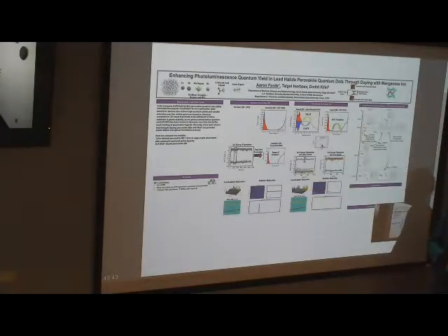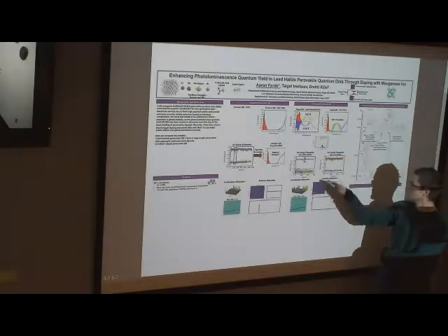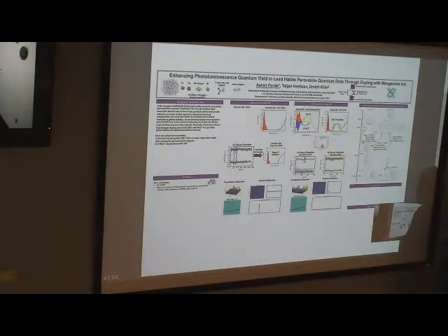There's no intermediate trap state that occurs in these systems, which is what you'd expect from a doped system, to be unaffected by ligands popping off on the surface. So we see no trap states along our trajectory for the doped system.